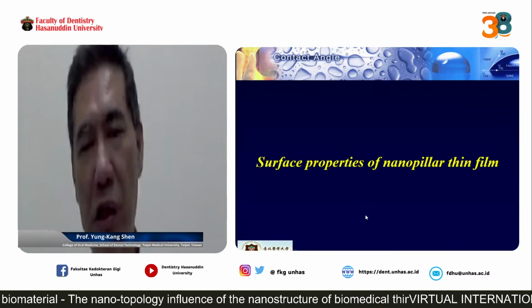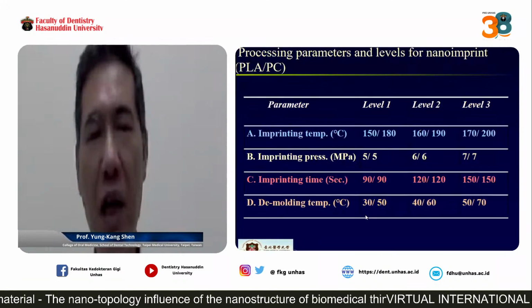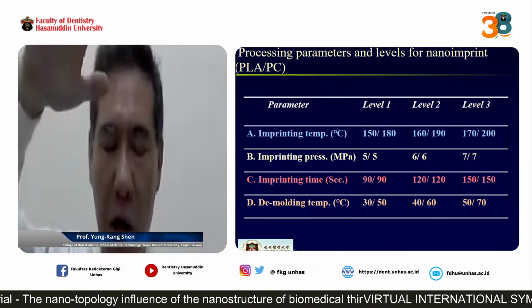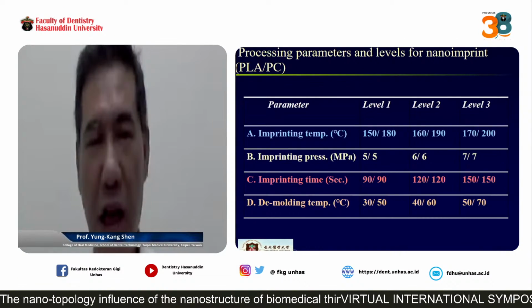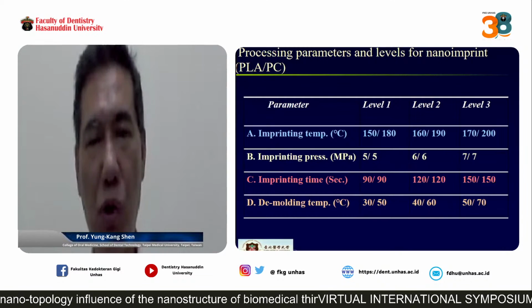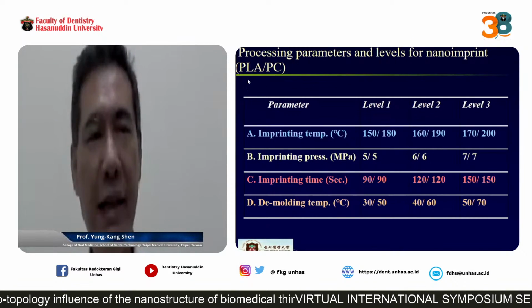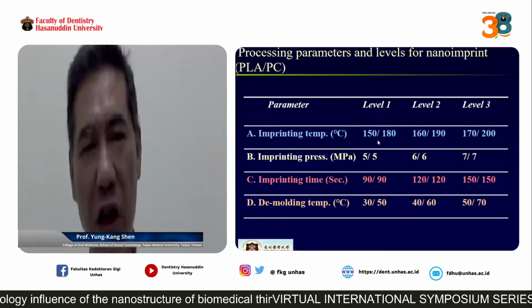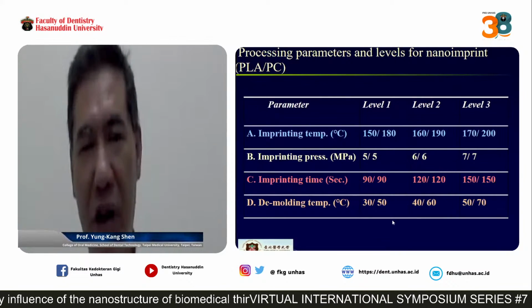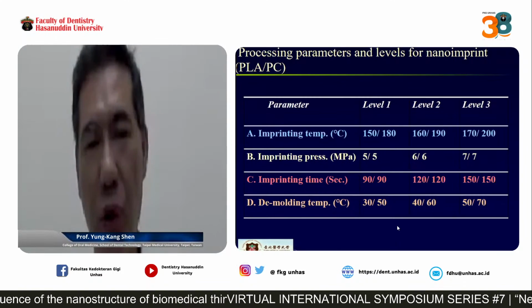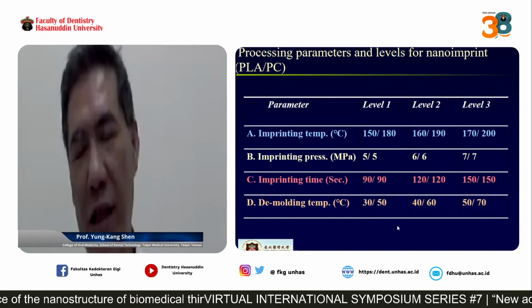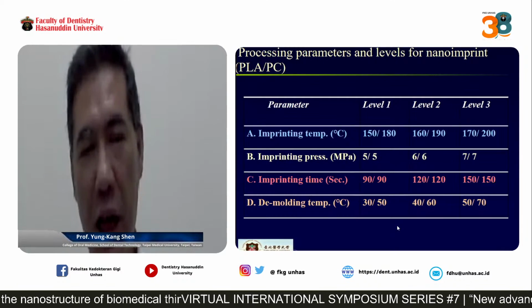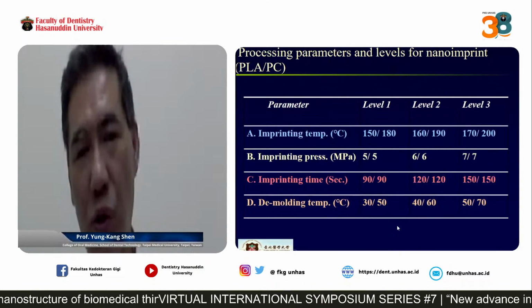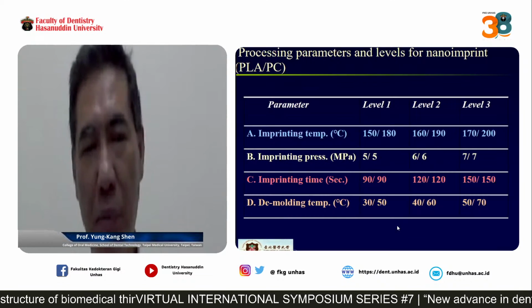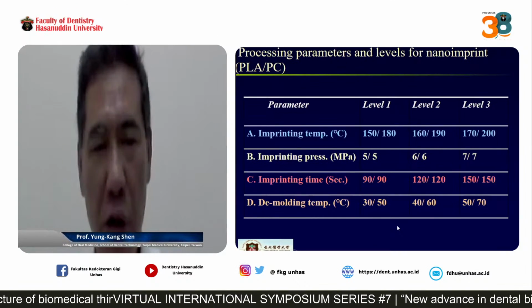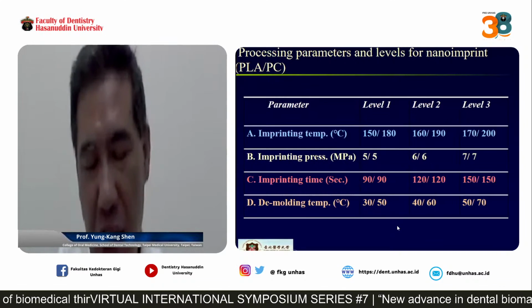So first, I will talk about the surface properties of the nano pillar thin film. You can see we use the imprinting process to imprint the nano pillar on here. So we use the imprinting temperature on here, for PLA in here, PC in here. So the processing is very different. This belongs to mechanical engineering, the way to produce the nanostructure on the PC thin film and the PLA thin film. Imprint temperature controls the machine temperature, imprinting pressure controls the pressure, and imprinting time controls how long we imprint on the surface.